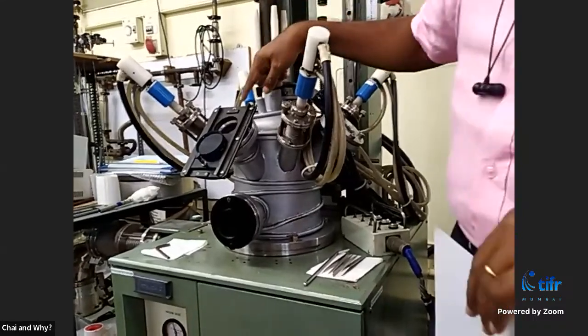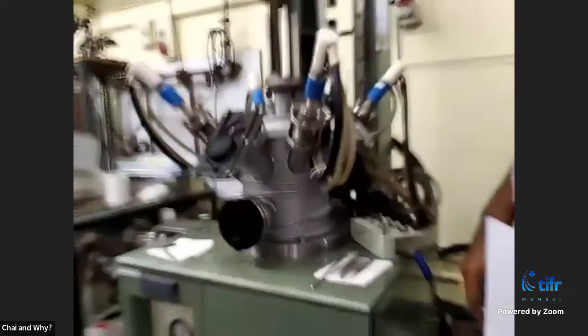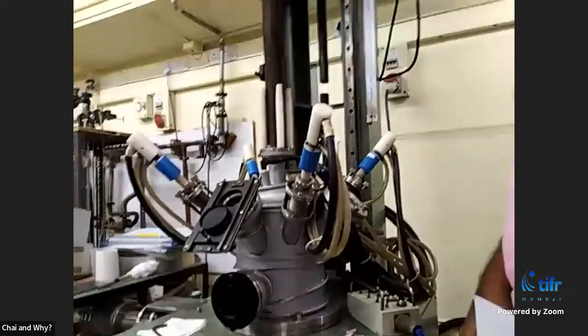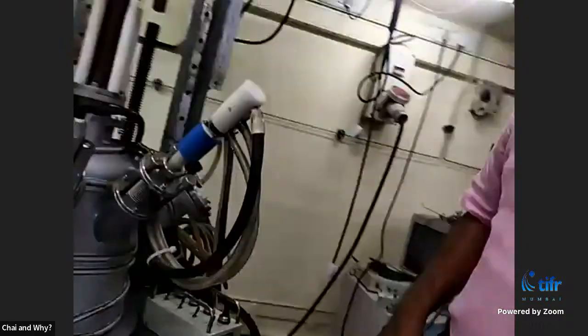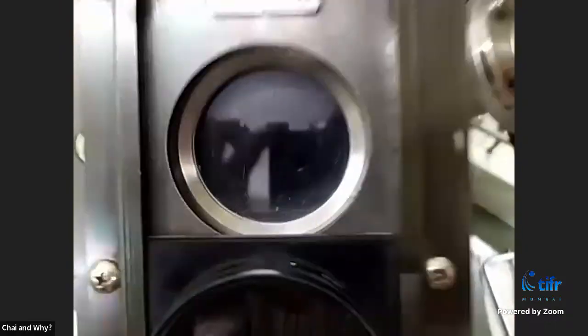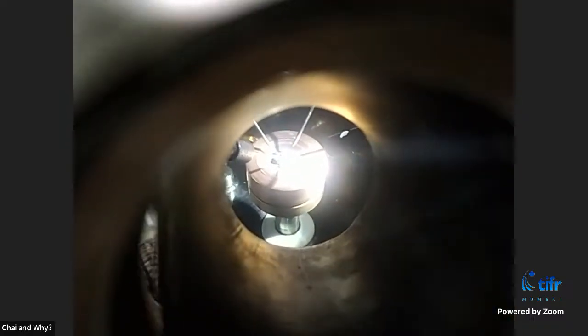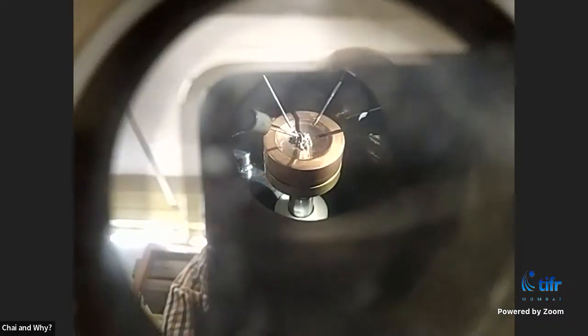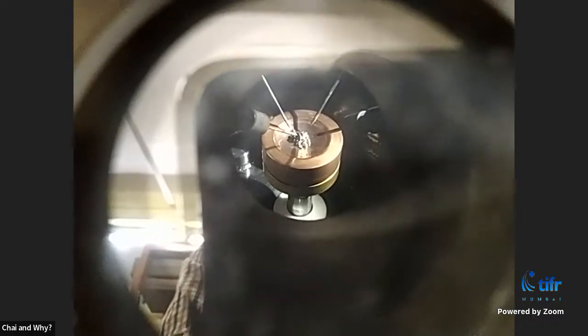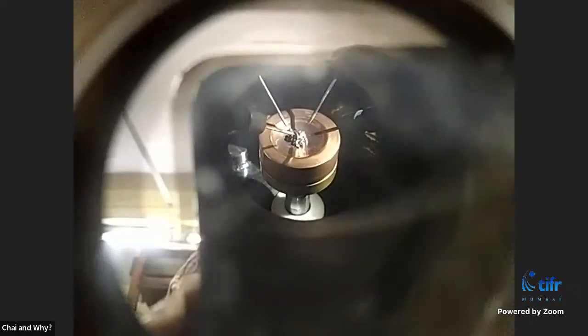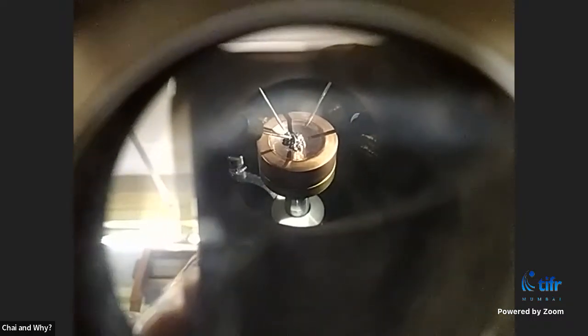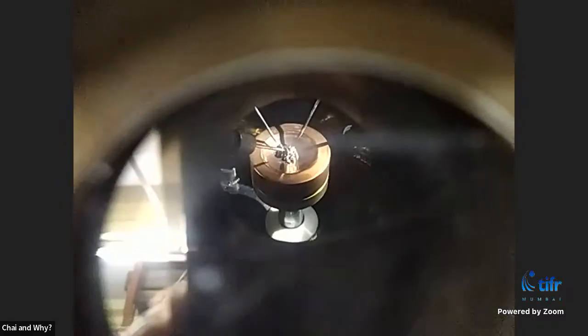So if you can show that inside, that will be good. So this is a tetra arc furnace. As you can see, there are 4 electrodes inside, and there are materials which are kept to melt, and these materials are kept inside on a copper hearth. That means there is a small holder, and the bottom portion is the hearth. The 4 needles that we see are the tungsten electrodes. We can pass current as high as 100 amperes to these tungsten electrodes, and we can melt. But to start with, we are not passing 100 amperes.